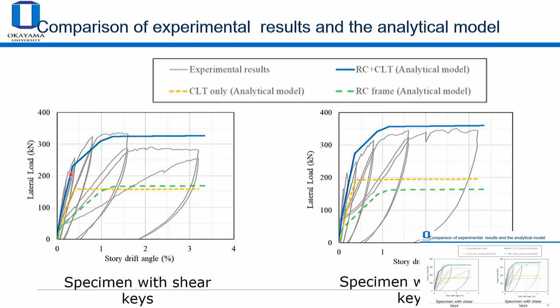So this blue line is the model, and this gray one is the experiment. You can see the initial stiffness is kind of well represented, and the maximum strength is kind of well represented. After that, there is degradation or splitting of the walls, which is not represented in this model. But usually for design, we need it until this point. This yellow one is the bilinear CLT, and this green one is the RC. If you combine both of them, it becomes this blue line.